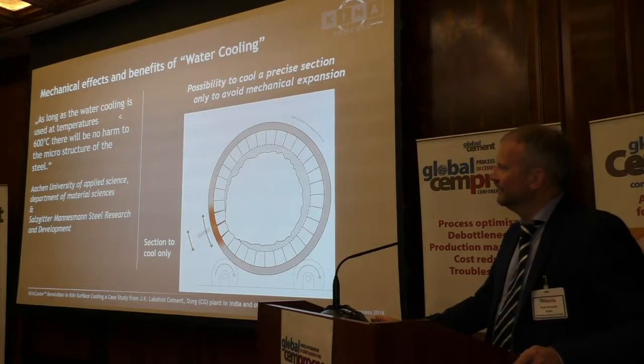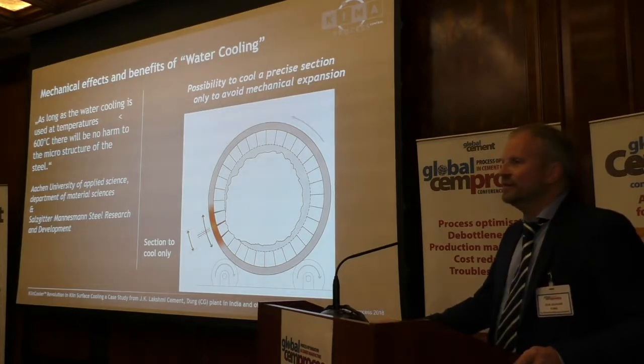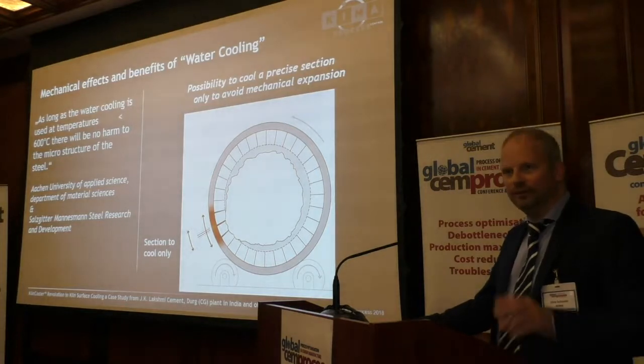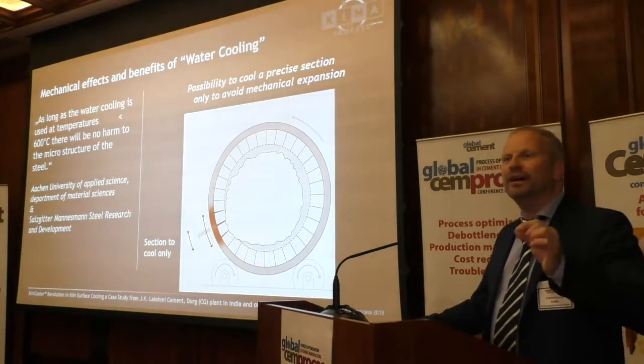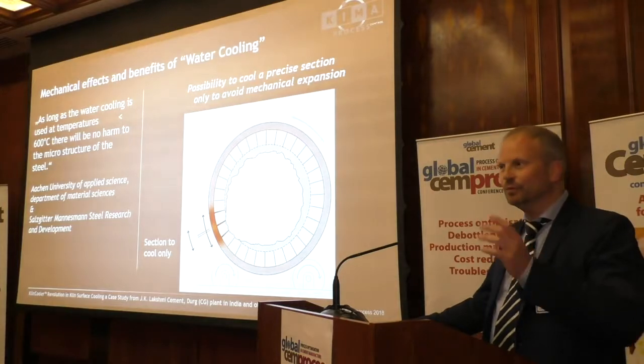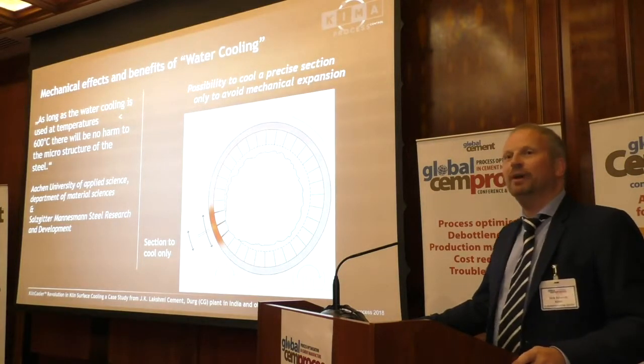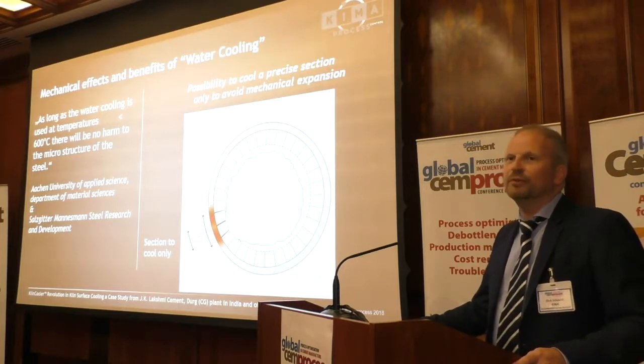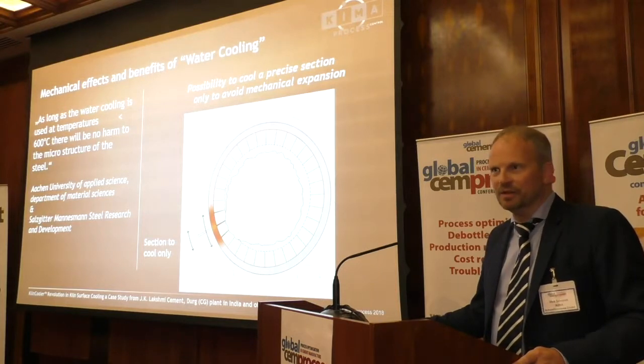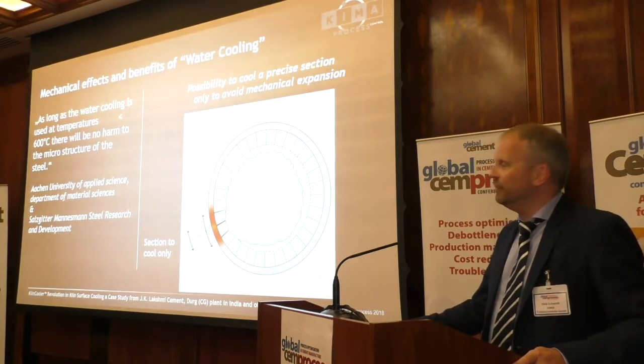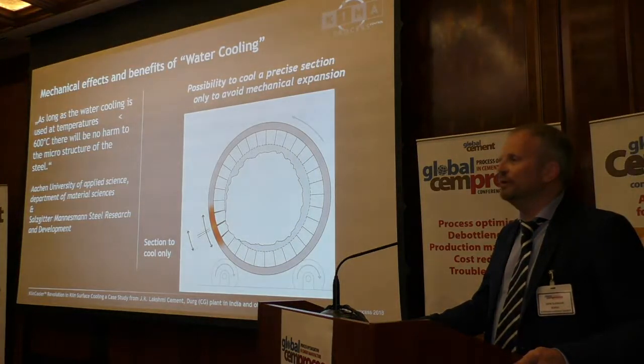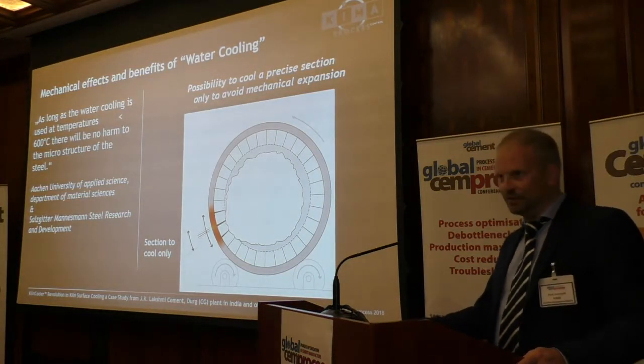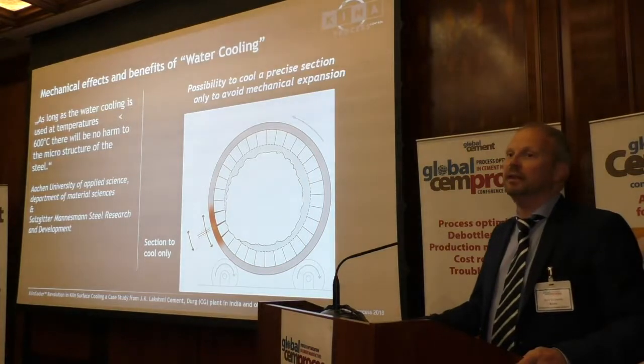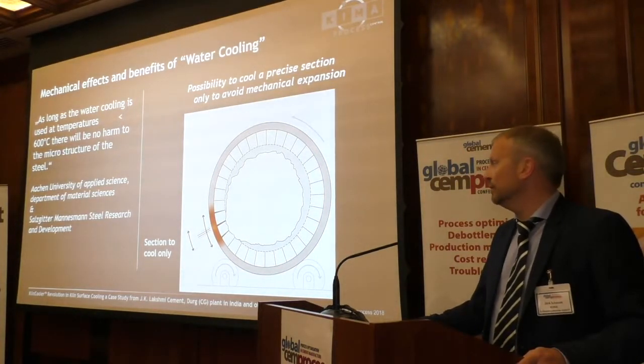Can these cause nozzle blockages? The nozzle opening, the hole of the nozzle, is approximately 1.5 millimeters, to give a feeling. We have a particle filter in front, in the system itself, which prevents particles larger than 0.1 millimeter. So we haven't had any effects so far. If you ask me for the necessary maintenance of such a system, it is exactly that here and there you clean the water filter.